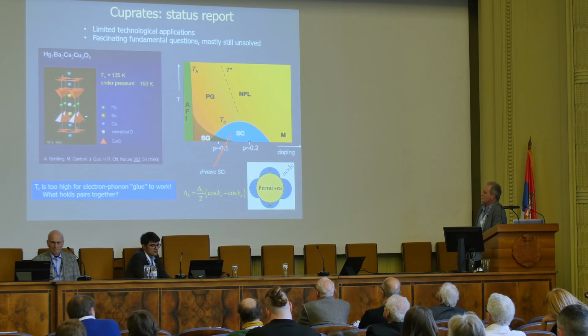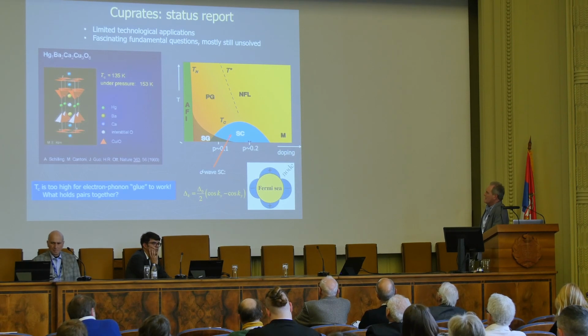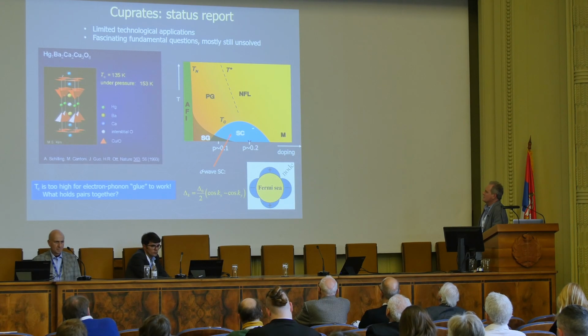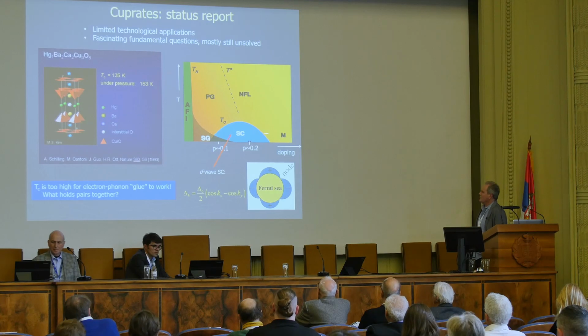Here's the crystal structure. You have a layer of copper and oxygen in every single cuprate, and then different spacing layers which control how you dope the system. The phase diagram is fairly universal. There's an antiferromagnetic insulator at zero doping. As you dope chemically, you get a superconducting dome. The TC is 90 Kelvin for the bilayer systems that have received the most attention. There is a famous pseudogap phase where non-Fermi liquid properties are observed above TC. And eventually, what I'll talk about tomorrow is this crossover to the overdoped regime, which is still controversial.